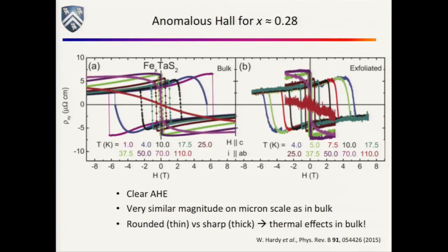So what I've shown you is things look very similar between the bulk and the little flake. Why do you care about that? Well, one possibility when we were first looking at this was, what can give you big magnetoresistances? It could be domains. It could basically be giant magnetoresistance. If you have a domain that's oriented like this and a domain that's oriented like this, you could really get this mismatching density of states thing, right, that would give you GMR.